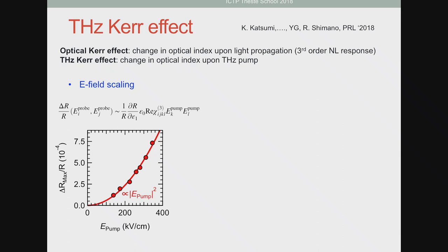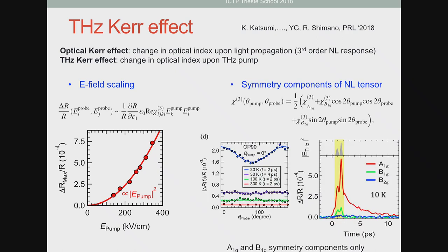And more generally, you can show that the change in optical reflectivity will depend on the third rank tensor that is written here, chi_ijkl, and that is going to depend on the E squared of the pump. So just like you did this game of extracting the symmetry component of this tensor in the case of Raman measurements, you can actually extract irreducible representations of this tensor using light polarization. And you can decompose your third order tensor.